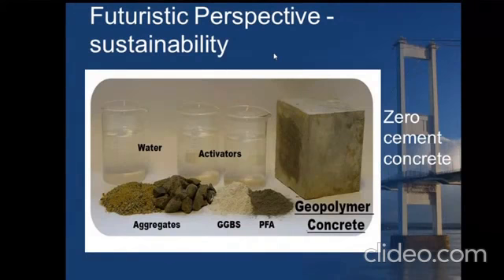I would like to highlight the major advantage in geopolymer concrete. We had a high temperature test performed for this geopolymer concrete, and we found that in a normal concrete, when the temperature exceeded 250 degrees centigrade, it started spalling. The concrete lost its binding capacity and it started falling into pieces. But on the other hand, geopolymer concrete enhanced its strength. There was increase in strength of geopolymer concrete. There was some reaction that was taking place wherein this high temperature actually facilitated the improvement in strength. So this was actually discovered by a fire accident that took place, I think, in a bridge tunnel in Australia, and later on all the bridge tunnel linings and the bridges in Australia are constructed using this geopolymer concrete. And I think in India we have to go a long way in order to implement this in practice, right? So this is a brief introduction about the geopolymer concrete.